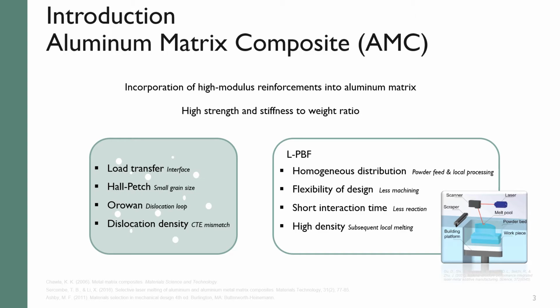It can enable homogeneous distribution of the ceramic particles, flexibility of design, short interaction time, which would mean less reaction time between the ceramic particles and the liquid aluminum, and finally high part density thanks to subsequent local melting.